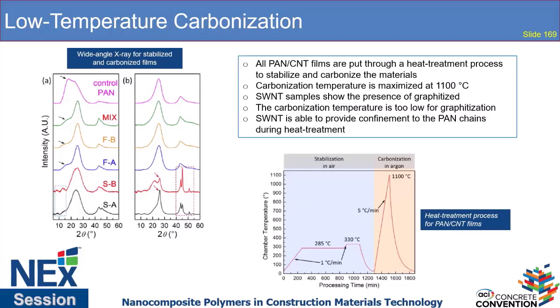Now why that's important is the single wall nanotubes have the smallest diameter, which means the polymer in that free volume, which is a small area, can get its arms around it a little bit better. You can form a more stable interface structure. But as you get a fatter and fatter nanotube, it's harder for it to form that structure, and that's really important in order to make the material stay dispersed. And again, these are not chemically functionalized. This is a physical interaction.